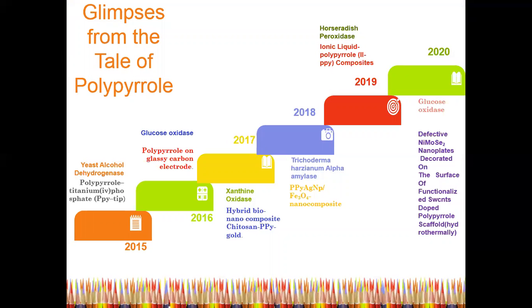We have here reviewed certain papers where polypyrrole-based conducting polymers and their composites were used as support for enzyme immobilization and made their mark in the field of developing biosensors. Elemental analysis data from literature showed that the composition of polypyrrole prepared chemically is almost identical to that of the electrochemical one. And here you can see throughout these years, the trail of polypyrrole is evident in different forms. In 2015, polypyrrole titanium 4-phosphate was used as a support for immobilizing yeast alcohol dehydrogenase. Polypyrrole was also immobilized on a glassy carbon electrode, and glucose oxidase has been immobilized onto it. In 2016, work was conducted to immobilize xanthine oxidase on hybrid bio-nanocomposite chitosan polypyrrole gold composites.